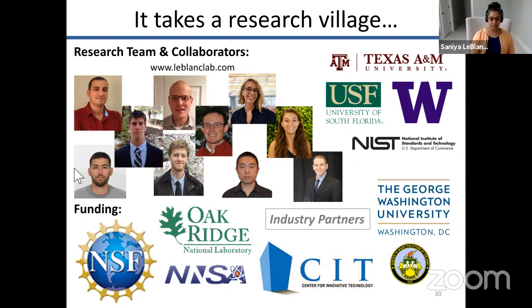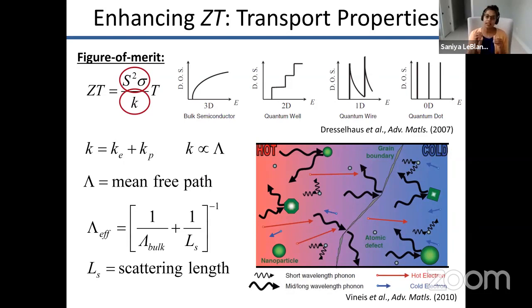So the density of states, I'll see if I can pull it up. I'll try to make it as simple as I can. So basically, it's the slope of that density of states that will impact the Seebeck coefficient. So if that slope changes significantly, you can significantly increase the Seebeck coefficient. So when you have these nanostructures, that's one aspect of how the nanostructuring will improve the electrical characteristics of the material. But when you can change the density of states so that the slope is changing significantly, that will allow you to get a larger Seebeck coefficient. So that's one way that nanostructuring can be used to improve the thermoelectric material performance.